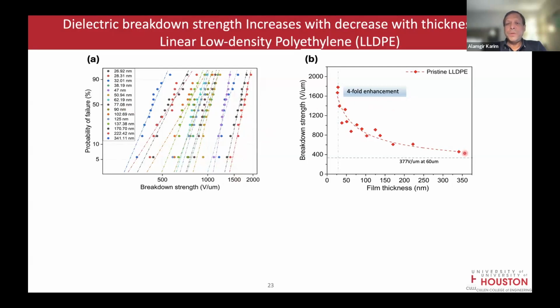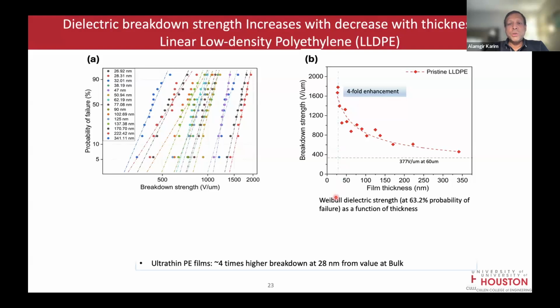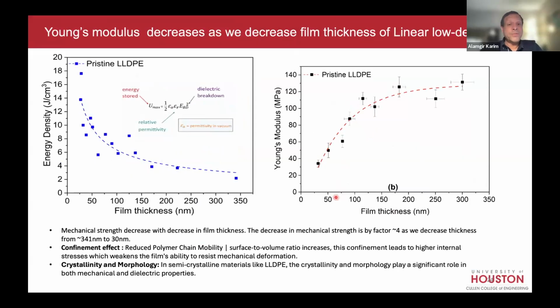Once again, in LLDP, you can see the ultra thin is about 4 times enhanced compared to the thick half micron kind of thickness. It's not as much as polypropylene, but it is still a factor of 4. Polypropylene was a factor of 10 enhancement. So these are just order of magnitude estimates, but just to show you that LLDP also, if you want to recycle it for energy storage, you can. The product of the square of the breakdown voltage times the permittivity still increases. So you're up from 3 joules per cc to about 12, 13, 14 joules per cc. Actually, it gets up to 18 in the best case. So not bad.